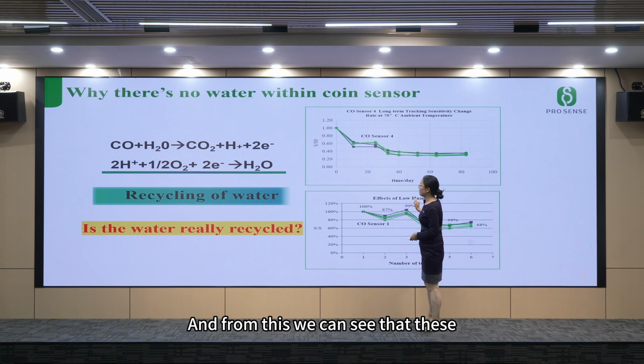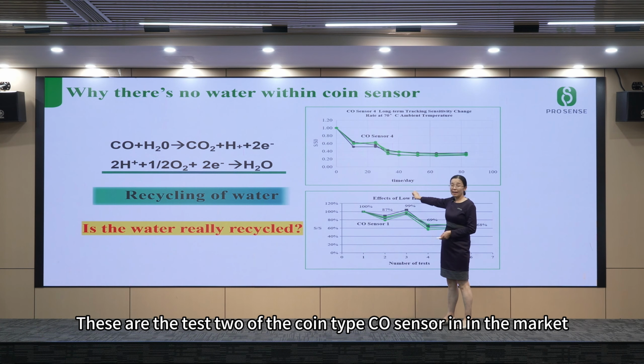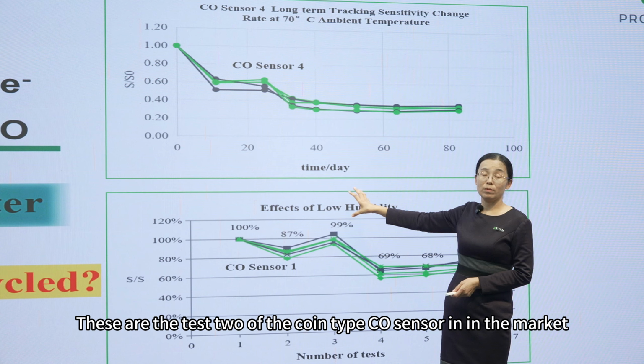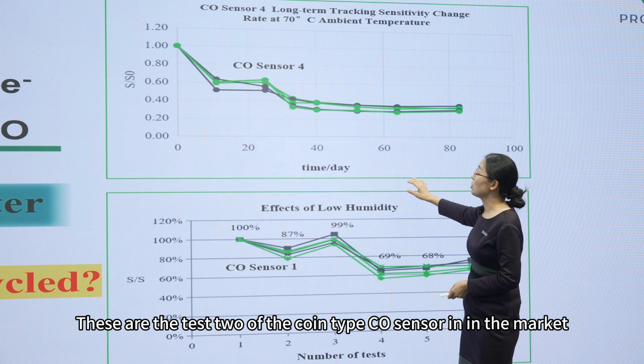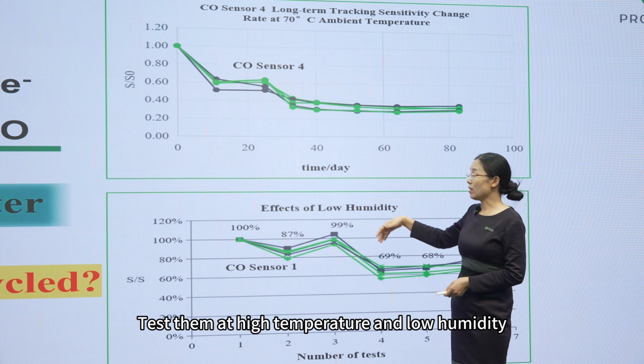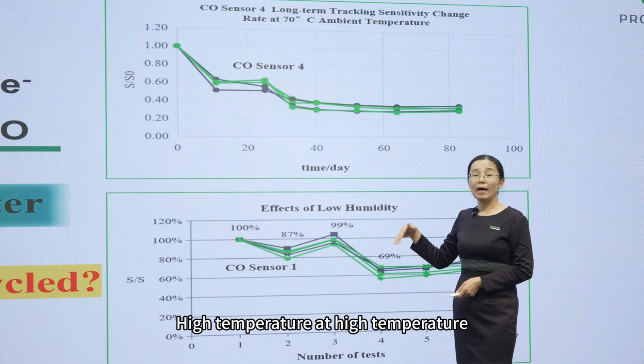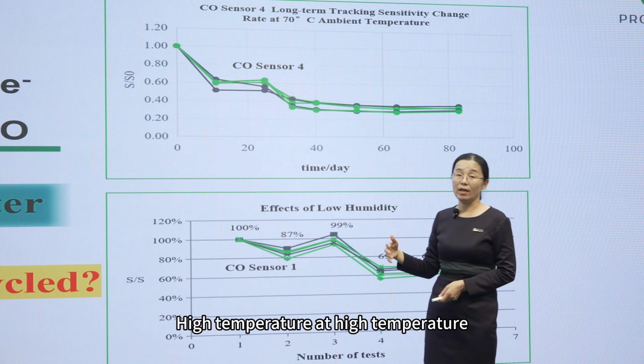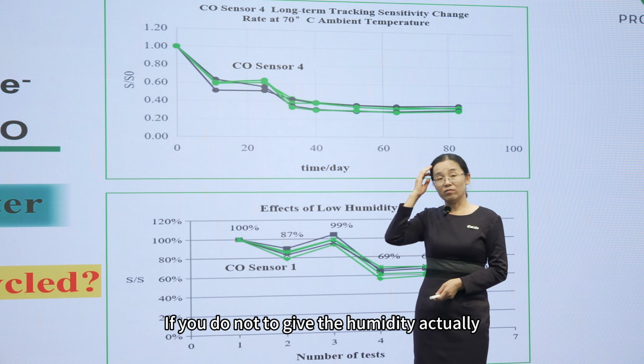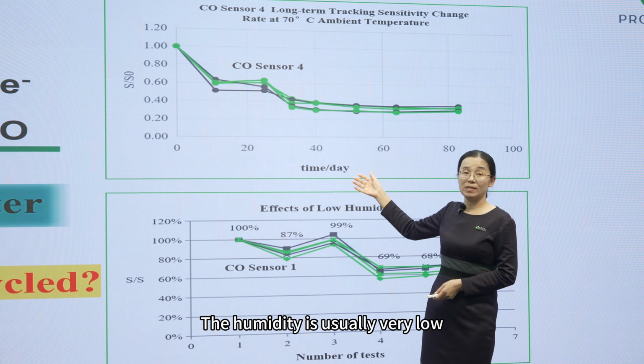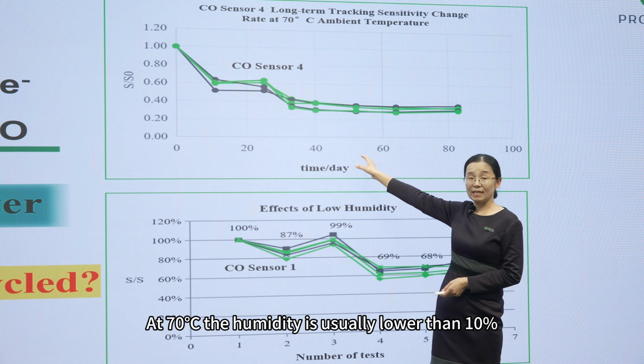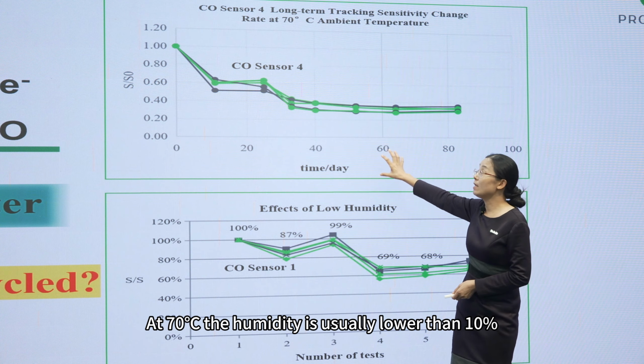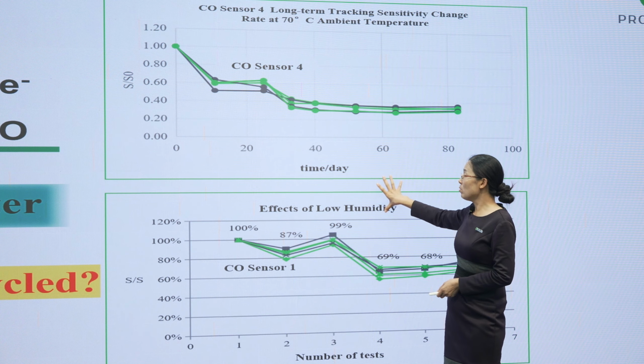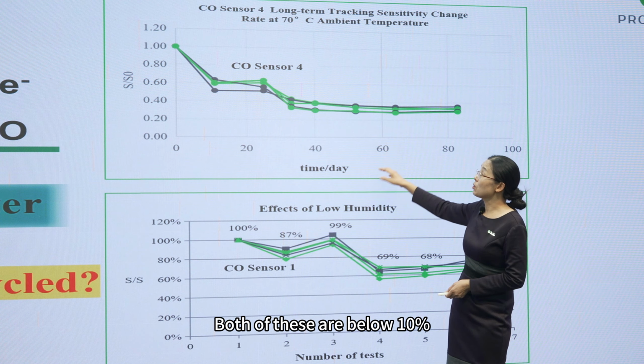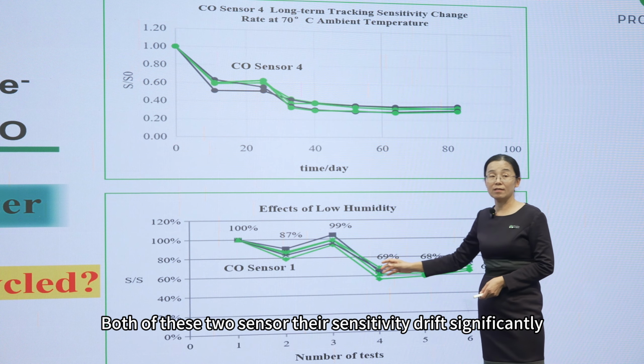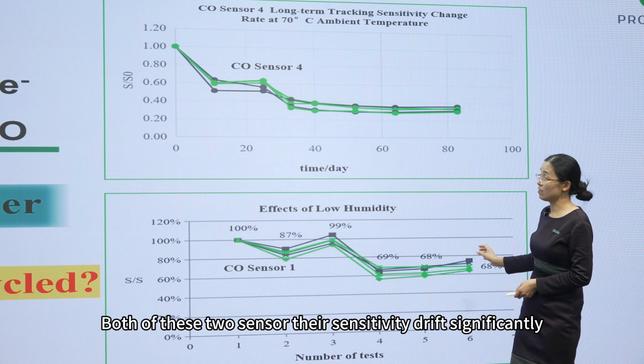From this, we can look at these tests. We tested two coin-type CO sensors in the market at high temperature and low humidity. At high temperature, if you do not add humidity externally, the humidity is usually very low. At 70 centigrade, the humidity is usually lower than 10%. Both of these are below 10%, and both of these sensors' sensitivity drifts significantly.